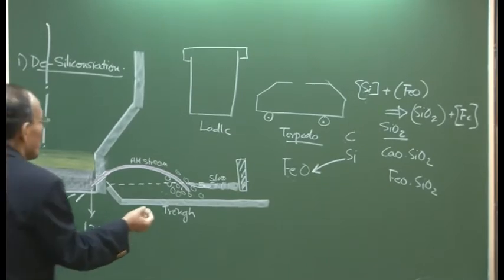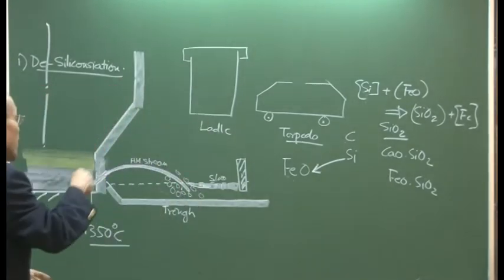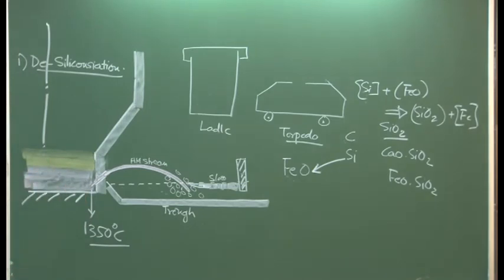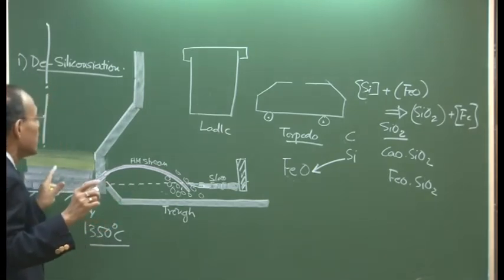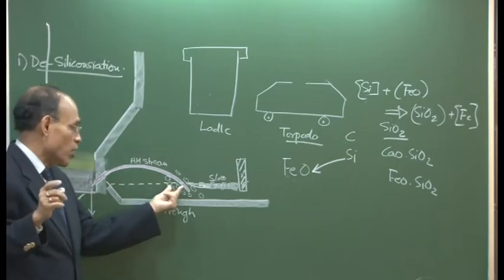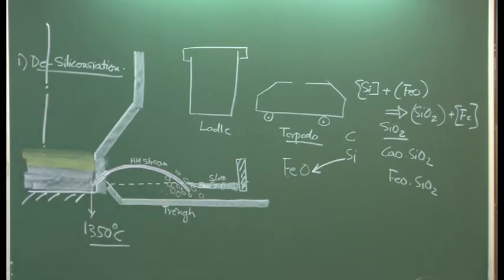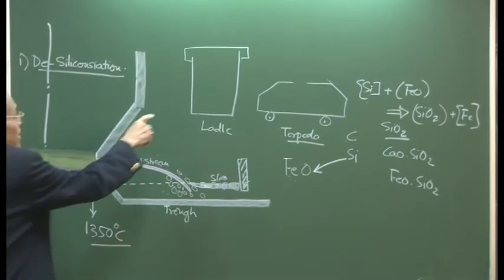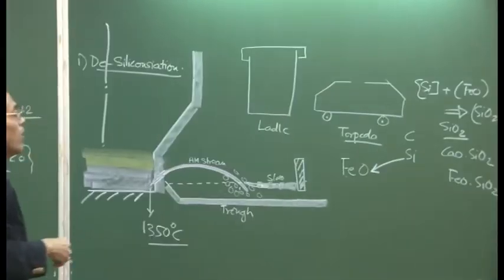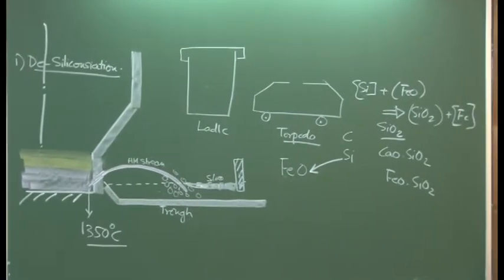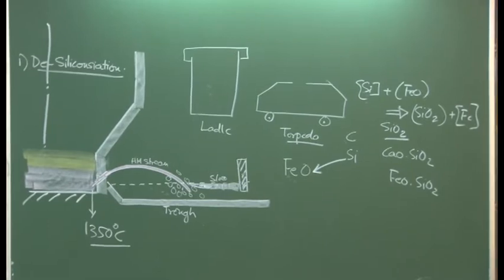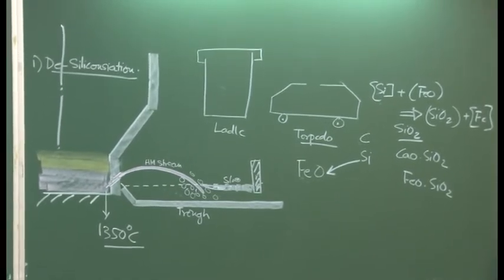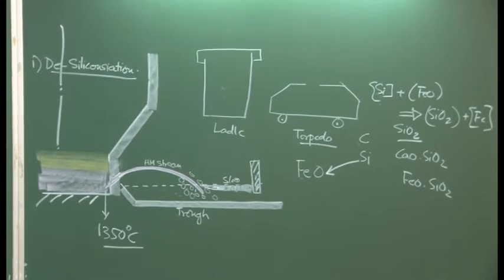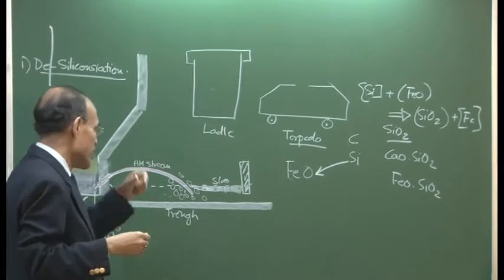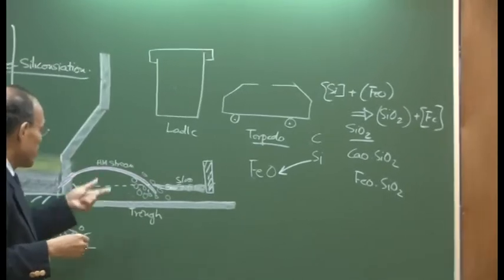So, you can inject nitrogen in the system, or if you have a paddle, you can start it with a paddle. But as I say, simple desiliconization is most popular in the blast furnace runner itself, if you do not have to do an extensive amount of desiliconization. Extensive desiliconization will require that you carry out the operation either in the ladle or in the torpedo. Now, this is enough for us, so we should be able to control. We can carry out thermodynamics and kinetics calculations and find out how much reagent should be necessary, what should be the rate of addition, etc.